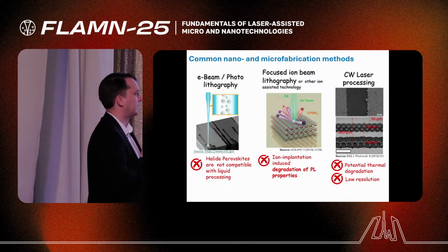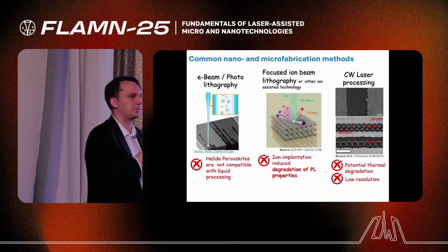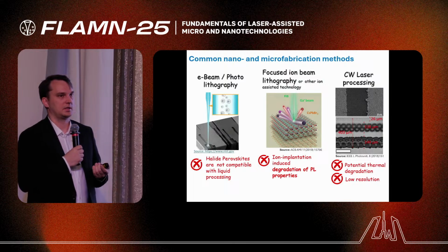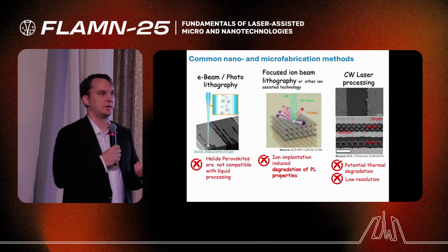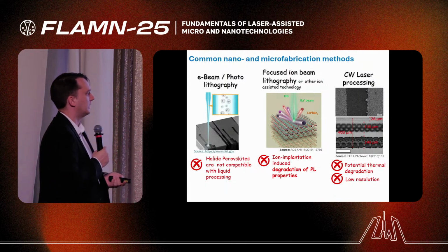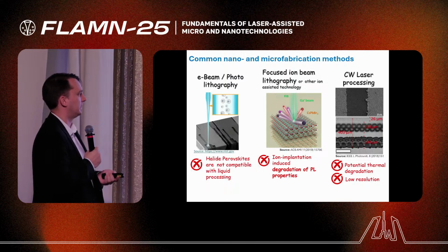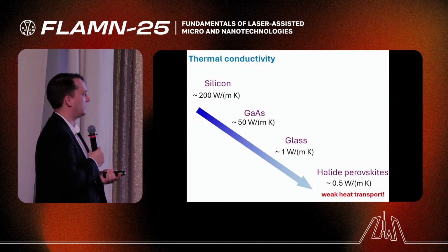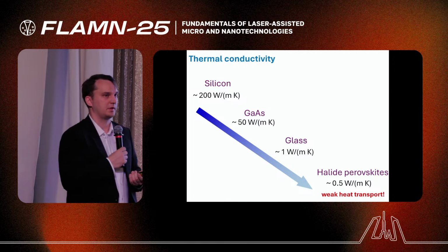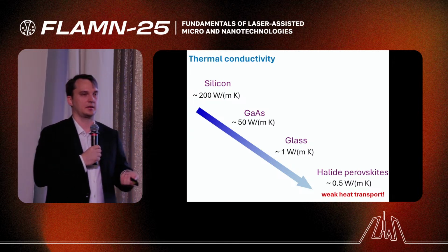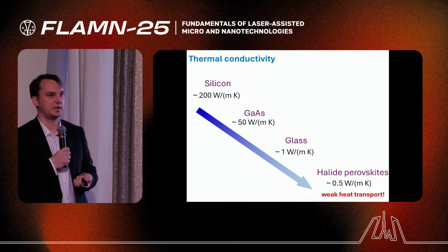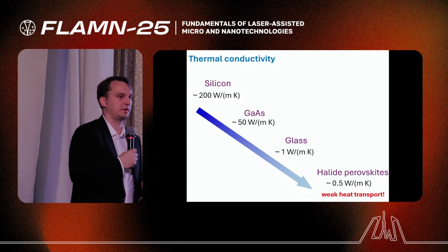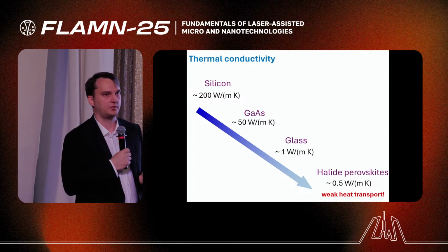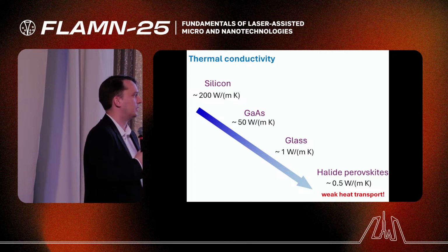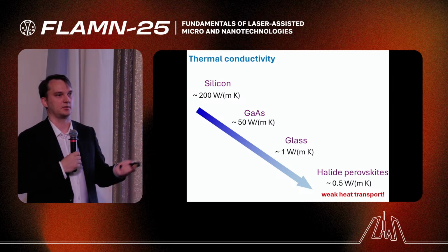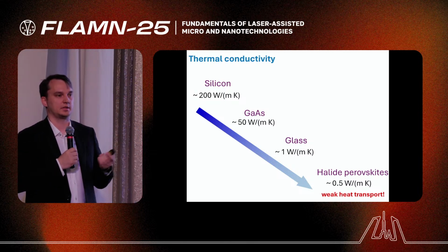And also there were some works on CW laser processing of perovskite, but the light emission properties and quality were not acceptable for many applications. So that's why we used a femtosecond laser pulse to make laser ablation much more precise. And we also use the fact that the thermal conductivity of perovskite is extremely low. It's lower than glass. So that's why the heat affected zone is really small.